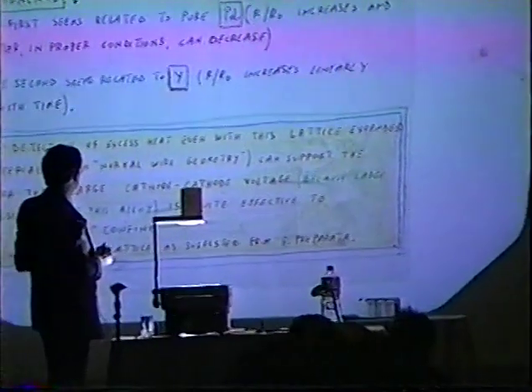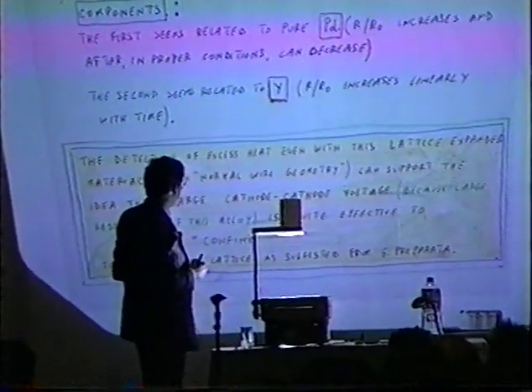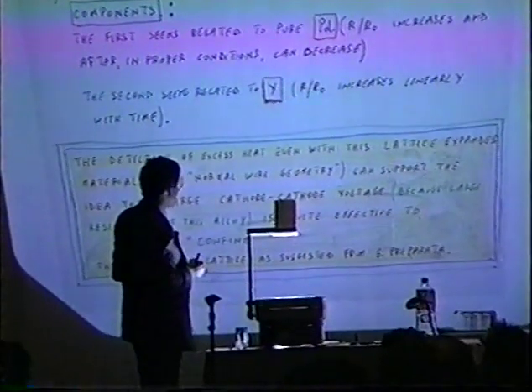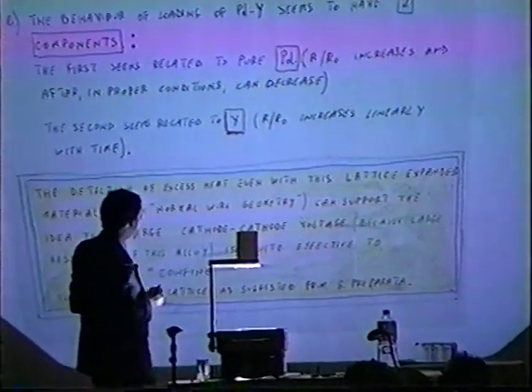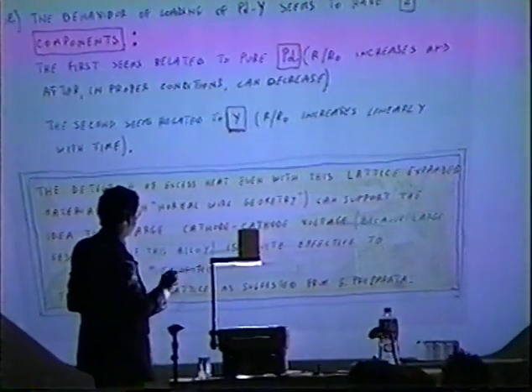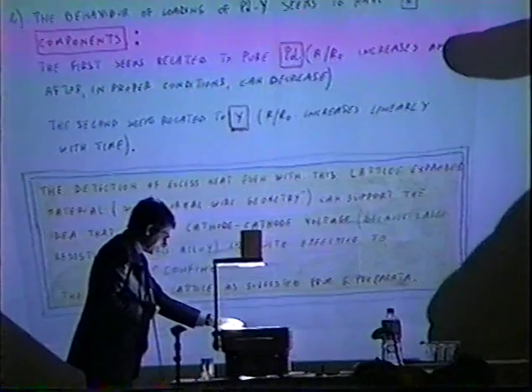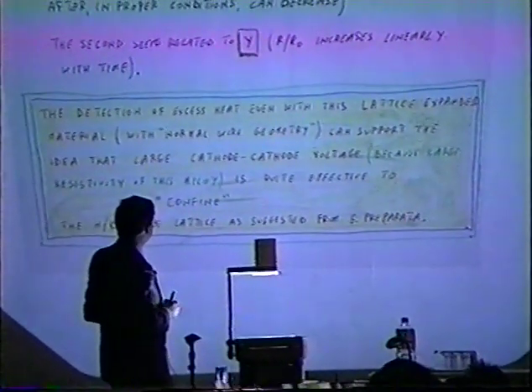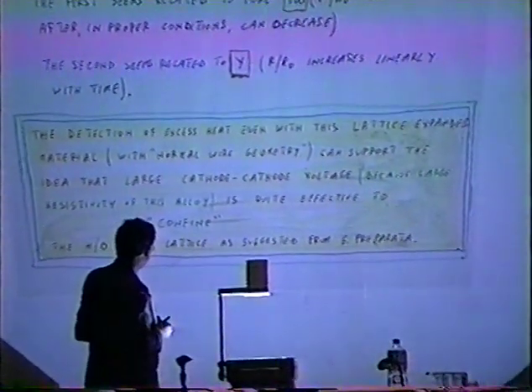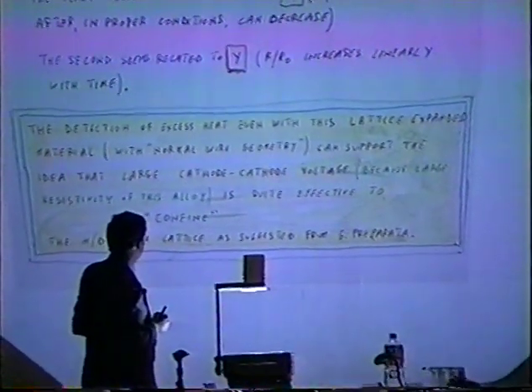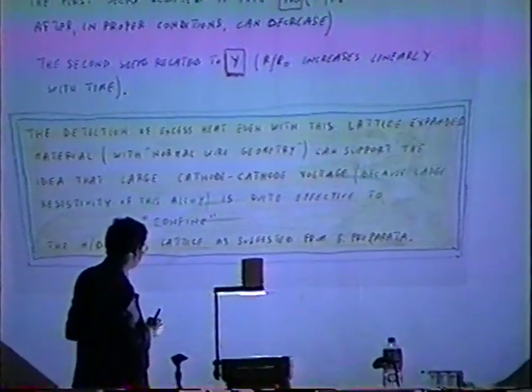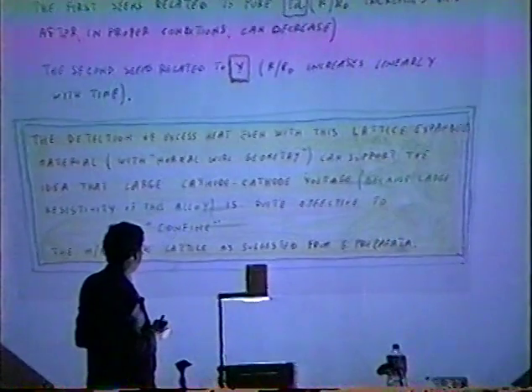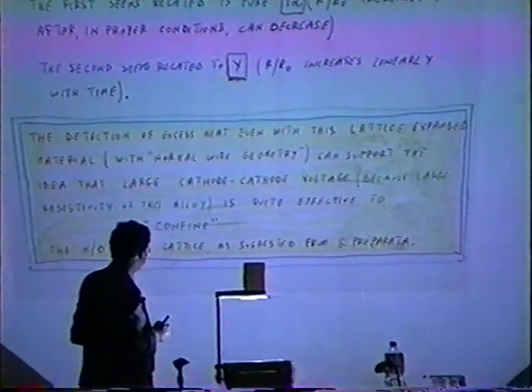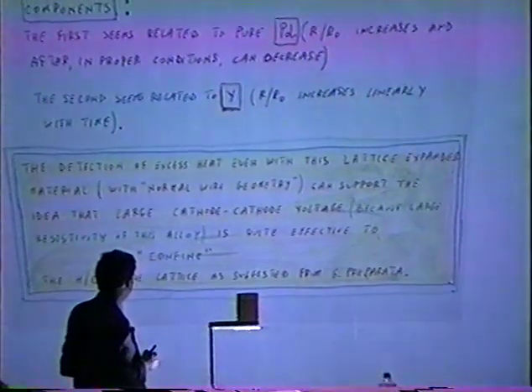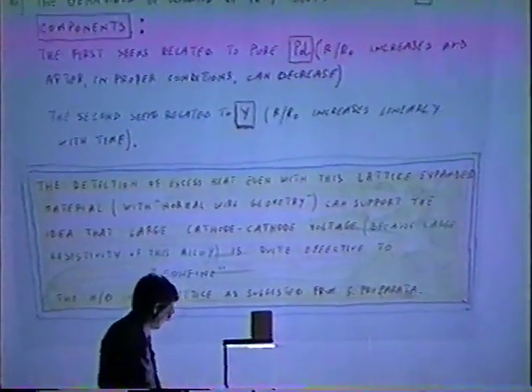And about the value of loading of this new alloy, since there are two components, one related to palladium itself and the other to the yttrium. Palladium reaches the maximum after the increase. Yttrium is slowly increasing over time. To stress this point, the detection of excess heat with this lattice expanded material, in the normal geometry, can support the idea that a large cathode voltage, because of the large resistivity of this alloy, is effective to confine in some way the deuterium inside the lattice, as suggested from the data.